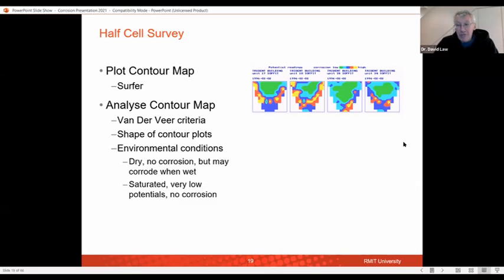And so these are the areas that we might want to look at in more detail to measure the corrosion rates and see how fast that steel is actually corroding and whether we can do anything about it. And we can look at these with a set of criteria that relate the steel potential to the likelihood of corrosion that are called the Van der Veer criteria.